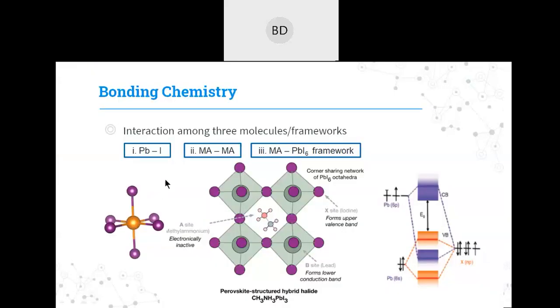Yes, there are several methods to reduce the degradation and increase the stability of the perovskite. There are three components basically: methyl ammonium, lead, and iodine. Methyl ammonium is very hygroscopic. So the first option is to change the methyl ammonium itself. The 2D perovskite you suggested comes from this. If you change the methyl ammonium with some larger cations, methyl ammonium is basically CH3NH3+. Instead of CH3, you take CH3CH2CH2NH3+. It's a long chain.